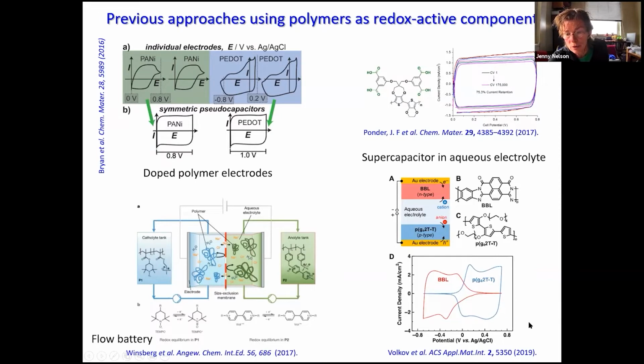The one below is a study from Linköping, a very nice study where you have a conjugated polymer with polar side chains and another polymer which has no side chains, and as a consequence it has to be deposited in a slightly more complicated manner than processing from solution, but nevertheless a very nice approach.